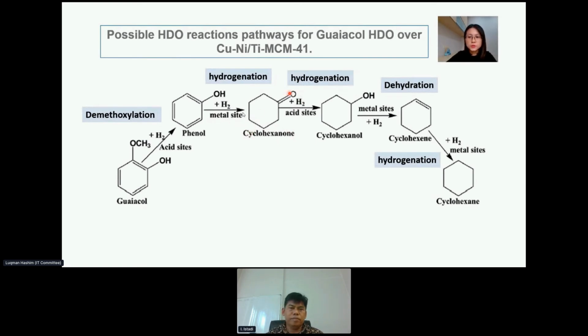Then hydrogenation will proceed further in the presence of acid sites, in order to reduce the double bonds into a single bond in the form of the alcohol cyclohexanol, followed by a dehydration process to remove the hydroxyl group in the presence of the metal sites, in order to form cyclohexene, and continue with the hydrogenation process in the presence of metal sites, and we will get our cyclohexane product.